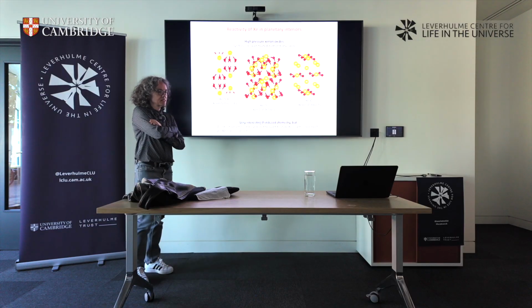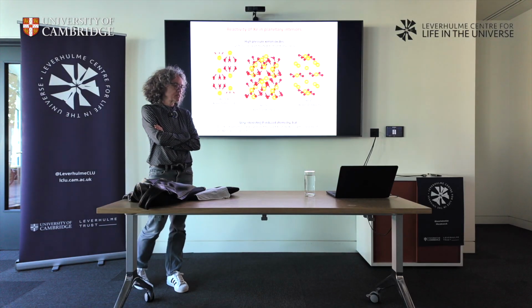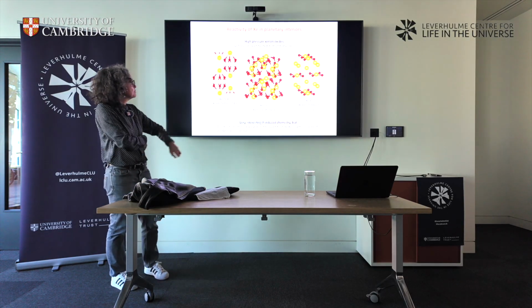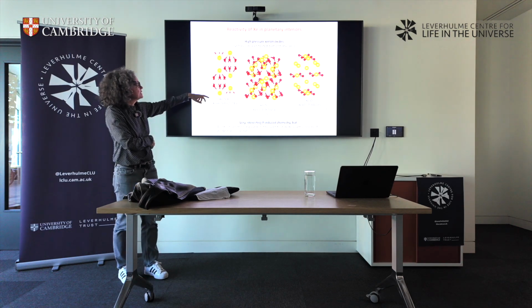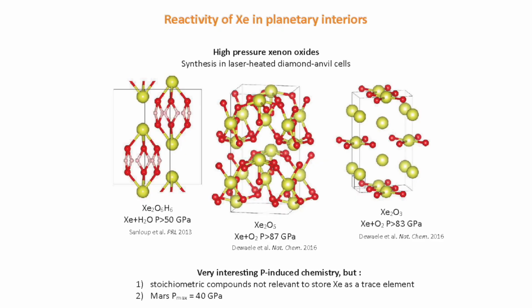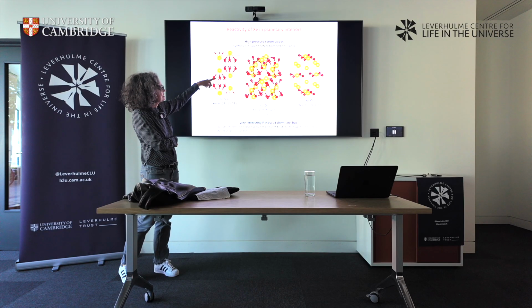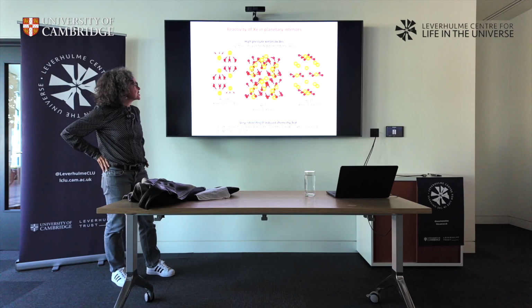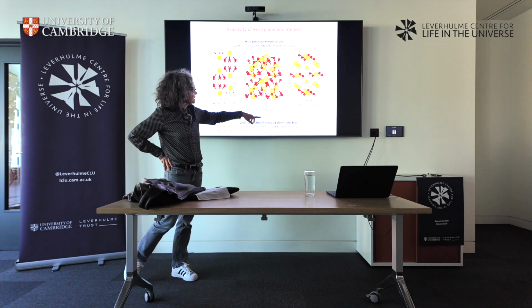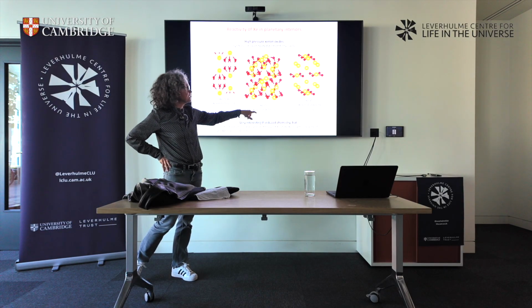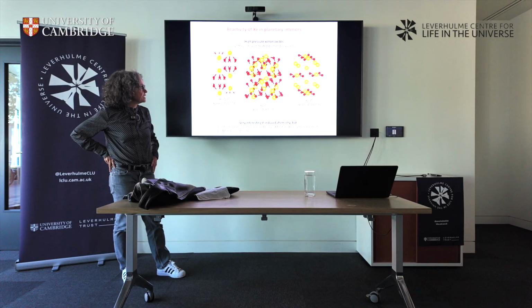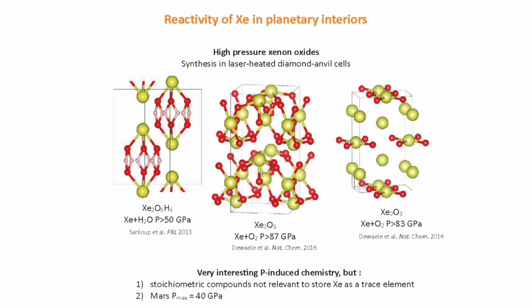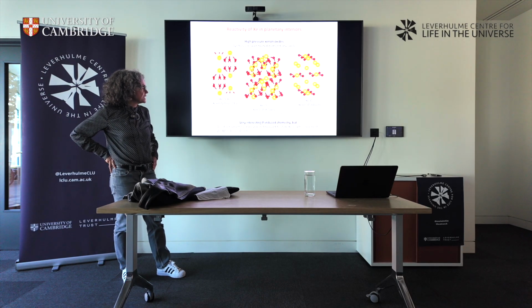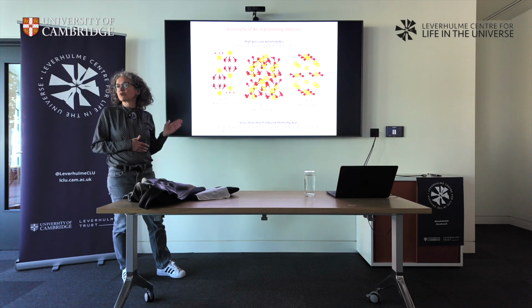We did some xenon-water experiments using diamond anvil cells, and we observed this compound forming. The yellow sphere is xenon, the red is oxygen, the pinkish is hydrogen. So it forms at mid-mantle pressures. After this synthesis, others came up with pure xenon oxide using the same technique, diamond anvil cell and laser heating. So again, it's very interesting chemistry. It's covalent bonding in all these compounds. It's very interesting, but again, it's too high pressure to explain the missing xenon.